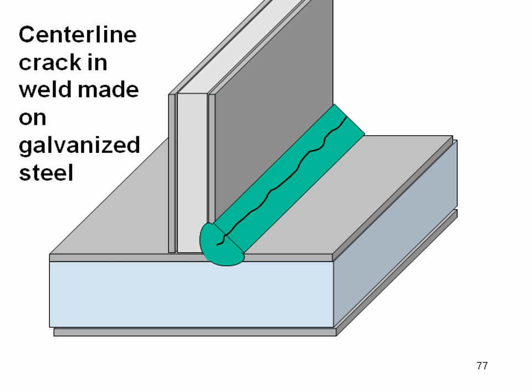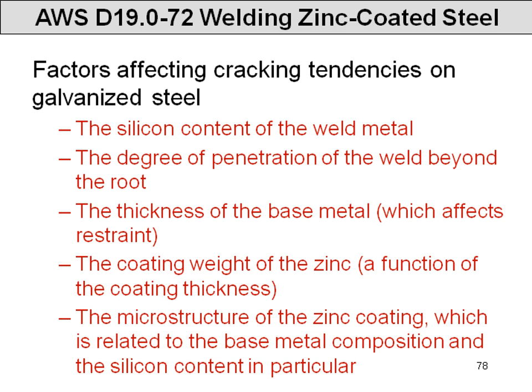Now, the American Welding Society has a publication that's now obsolete, D19.0. It was last updated in 1972. And I don't know if it'll ever be updated again, but in this publication is a list of factors that affect cracking tendencies on galvanized steel. The factors include the silicon content in the weld metal, the degree of penetration of the weld beyond the root, the thickness of the base metal, which affects restraint, the coating thickness of the zinc, and the microstructure of the zinc coating. What I take from this list is there are a lot of things that affect cracking tendencies. Nobody said our job was going to be easy, but we have a lot of variables now that we have to deal with.